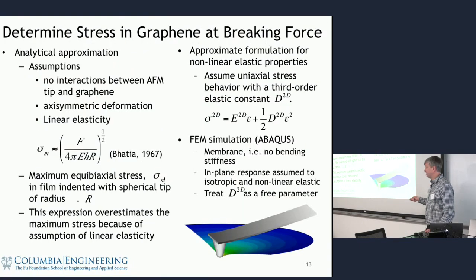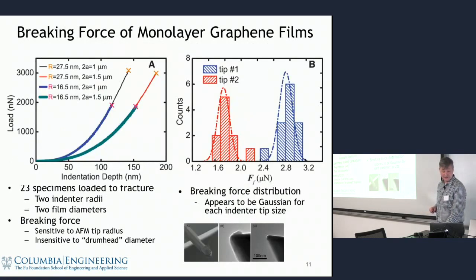Really what that's telling us is that all of the action is here. Our fracture is not due to the bulk force displacement response of the membrane. It's all due to the local stress concentration under the tip. So that's very interesting, and we could plot that. This is the fracture force for the 2 different tips, and you can see we get what looks to be kind of a Gaussian distribution. That distribution actually turns out to be interesting as well.